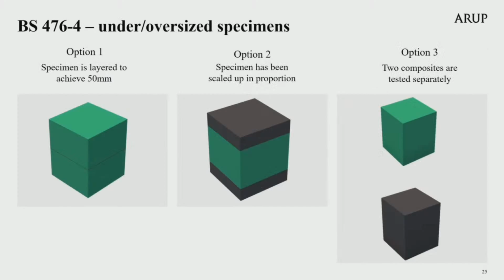If the thickness of the material is less than the height required of 50 millimetres, each specimen must then be made of a sufficient number of layers to achieve this thickness. These layers should occupy a horizontal position in the specimen holder and be held together firmly, without compression of the specimen, by steel wires to prevent air gaps.